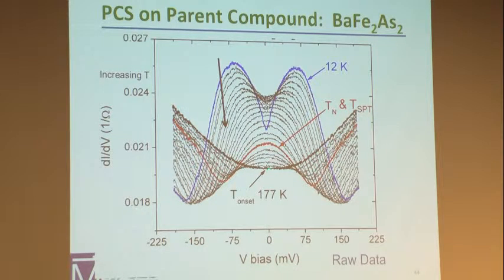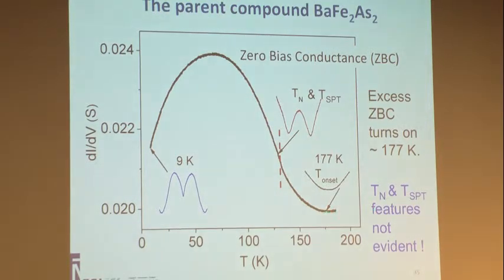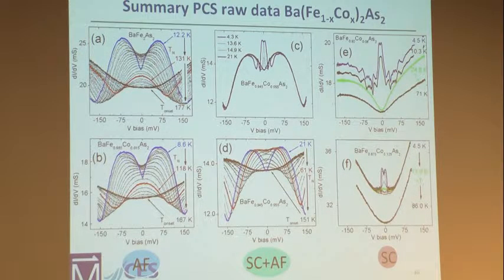Now what I'm going to do is sit right here at zero bias and look at that as a function of temperature. This, remember, is the normal state. This is the parent compound. There's no superconductivity there. We see the zero bias conductance sails right through the structural magnetic phase transition and just keeps coming up. It's got that dip in the center. Okay? We don't see these phase transitions, but we see something turning on at 177 degrees. Hamoud went through probably thousands of spectra by the time he got his PhD. But he found out where he got this excess conductance and where he didn't. And he took a lot of data like this, which shows this excess conductance around zero bias, plus the Andreev reflection in the center. So if you could take this and model it to see the quality of the Andreev reflection, that was helping to determine our diagnostics for making sure we had good point contact junctions.